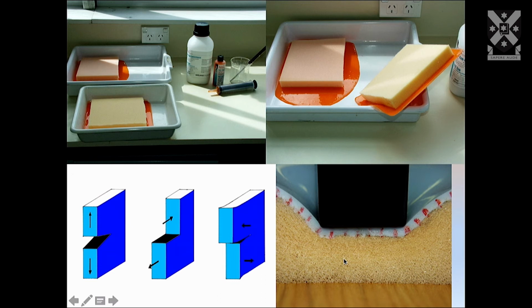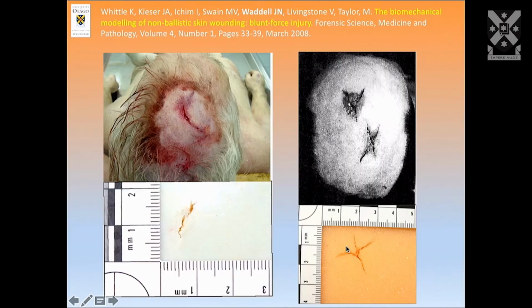The moment you hydrate the sponge, you get a totally different reaction. The hydrostatic pressures are such that as you impact it, it cannot escape. And what happens then is the underlying tissue ruptures and the skin ruptures. And effectively, it's rupturing from the inside outwards because of the hydrostatic pressures from the blunt force trauma. And we were able to correlate this with post-mortem evidence. And again, let's say we were successful in publishing this.